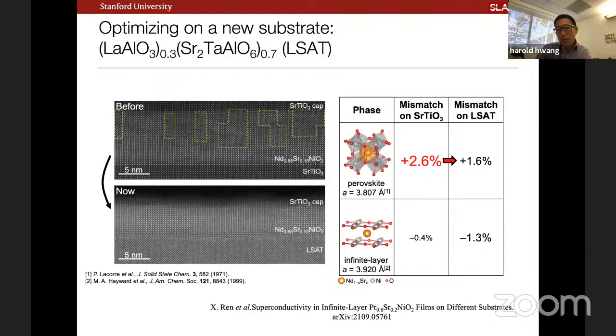But if we then compromise in a different way by going to LSAT, we can make the perovskite a little bit more energetically happy, but then at the price of going to compressive strain in the infinite layer compound. So it's a little bit of this push-pull business, but in terms of these extended defects, what's exciting is this largely eliminates them, right? So we can now grow nice films where we see no apparent extended defects largely across the film. I should say that the first report of thinking about different substrates for the infinite layer nickelate system was this reference here on the arXiv.